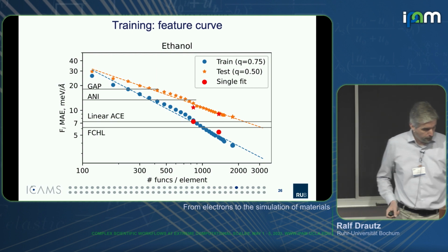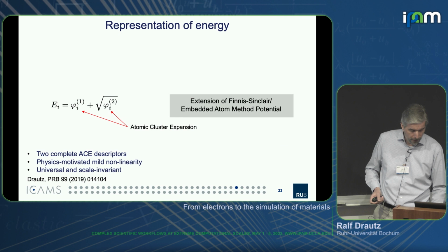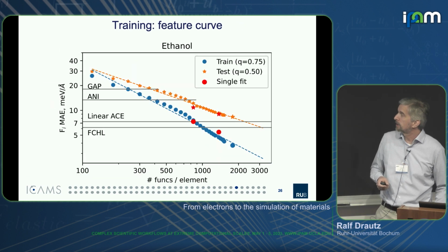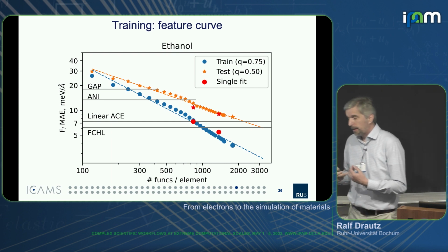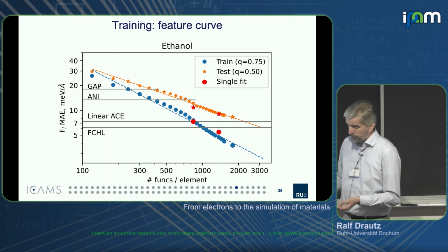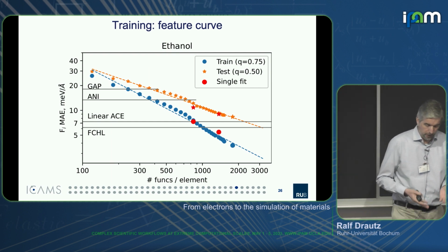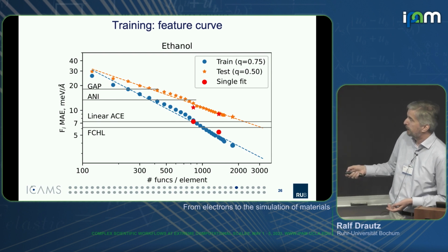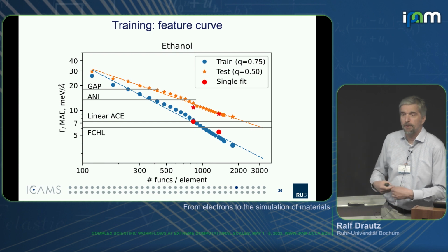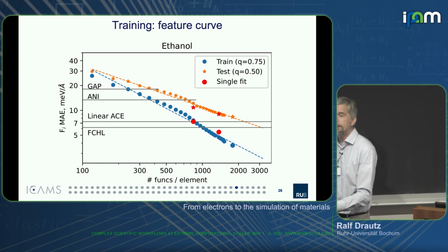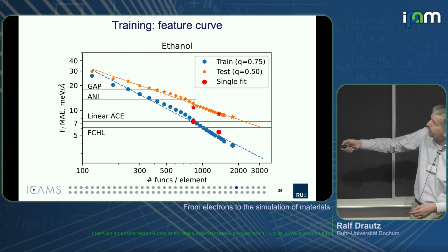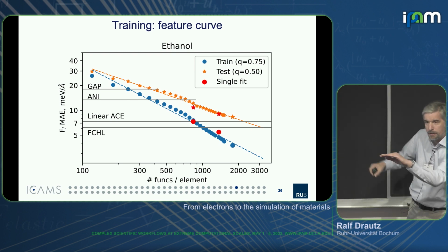But we have fitted here, if I may go back a few slides, this nonlinear term. Actually, we looked at this. How much does this nonlinear term give us? We need about 10 times fewer parameters to achieve the same accuracy as the linear ACE. So starting from physical insight helps. Essentially, you start lower at few parameters and then go down.